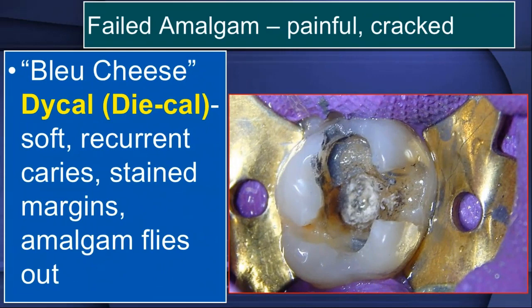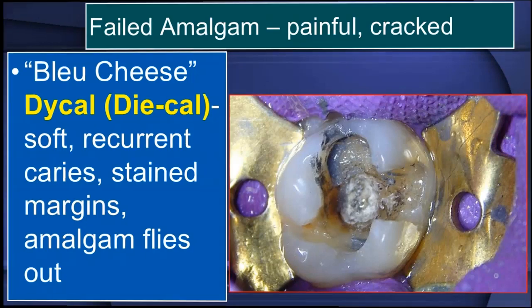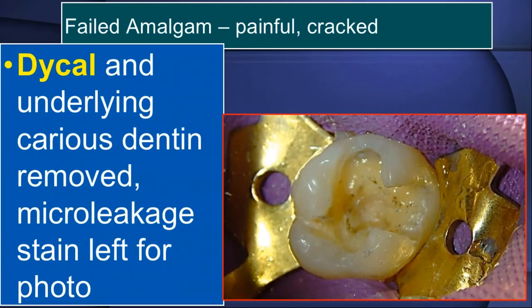So I slid this on. I said, let's take out and see what's going on. And the Dycal underneath had dissolved. The amalgam flew out. It was not well condensed at all, naturally. And of course, you know, there was no rubber dam on because of how they adjust the occlusion, right? And then underneath, you can see a lot of stain. I left that stain there so you can see where it had leaked all around. And then I removed all the very soft, you know, mush that was underneath the Dycal. The Dycal was very mushy and all that.